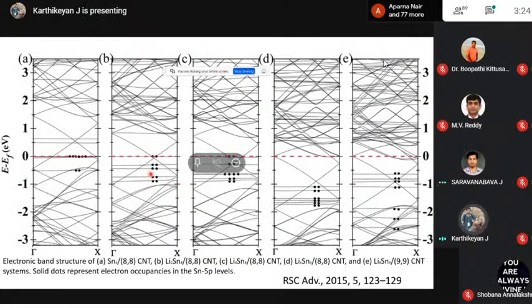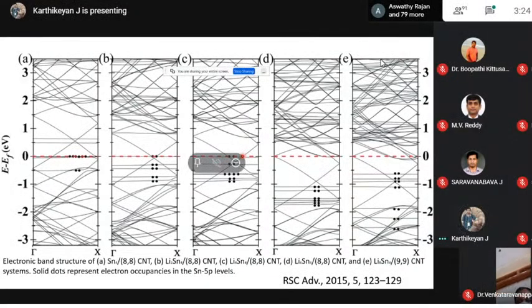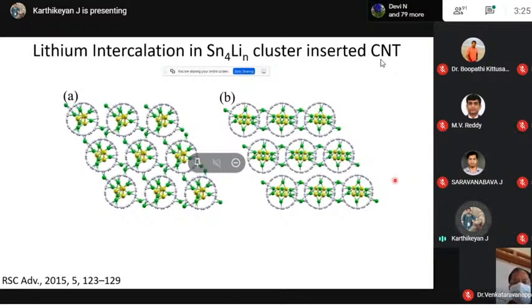So when you add Li to Sn4, you can see that this is the band position that you can take as a reference. When you add a lithiated cluster, it comes down. That means this band is now occupied. So now if you add more and more lithium, that same position is going down. That means more and more CNT bands are occupied. But after a certain limit, that cluster is not donating much charge to the CNT. And what is happening now, after a certain limit, the lithium goes to the interstitial voids of this CNT assembly. So now the intercalation is happening between the CNTs.